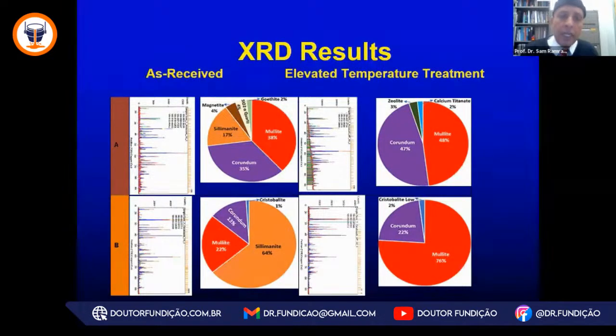Certainly, the elevated temperature exposure of these materials changes their compositions, the compounds. They are naturally hard compounds, but the proportions of these hard compounds change as well. And certainly, these hard compounds are brittle, and when exposed to impact and abrasion, they change the distributions rather quickly. And the heat from these processes can also make phase changes and new compounds in the materials after reclamation as well. So at the end of this, what we found in that AFS study is there is no panacea.